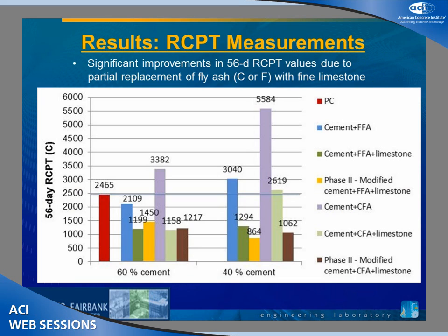I'll just quickly go through the transport results. Gary Knight mentioned earlier today that he's seen some really good results when you put limestone in with fly ash systems. We're seeing the same thing here. We can just focus in on the rapid chloride permeability numbers. We have the control at about 2,500. These are at 56 days.